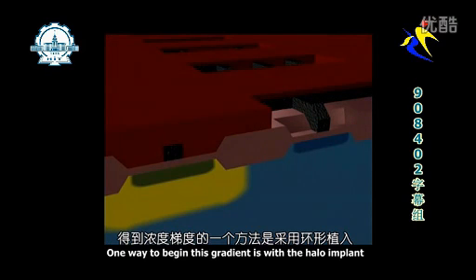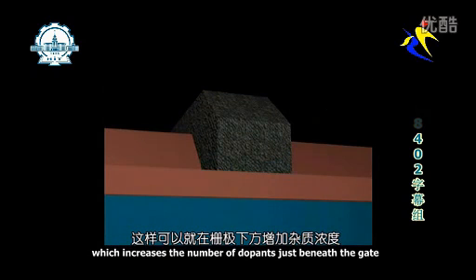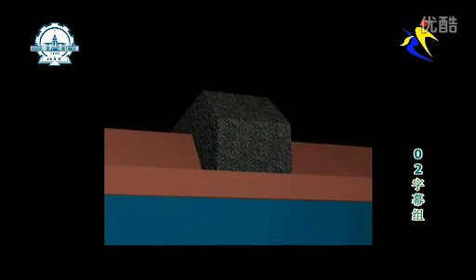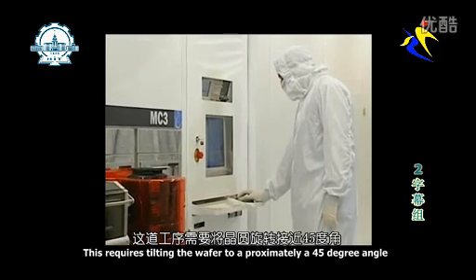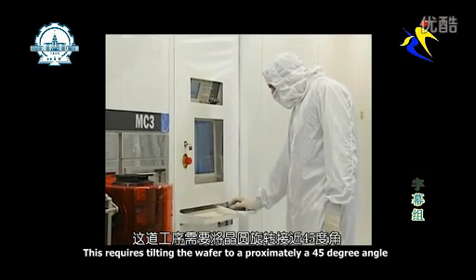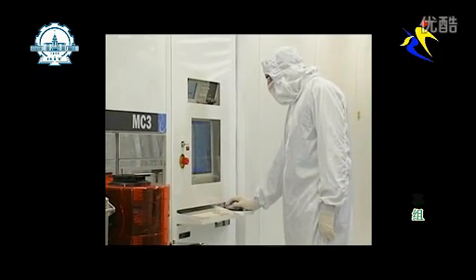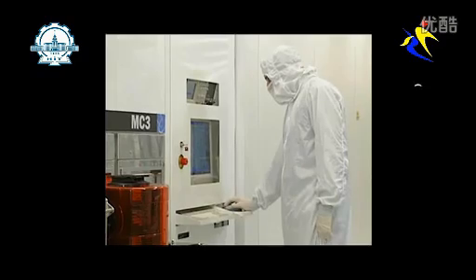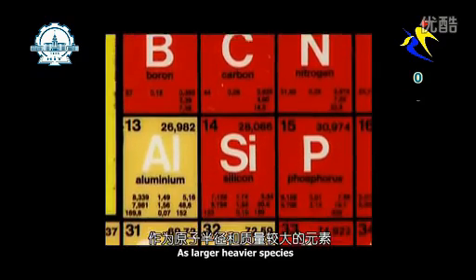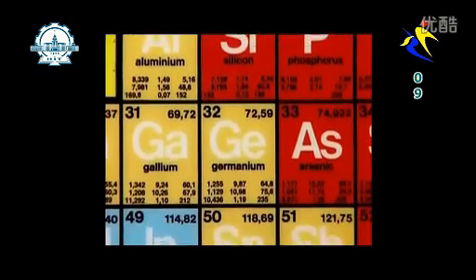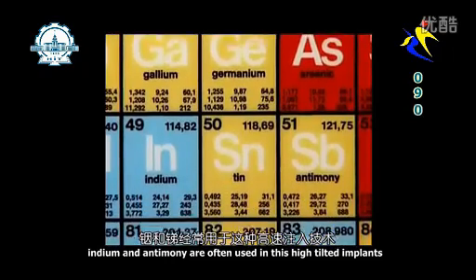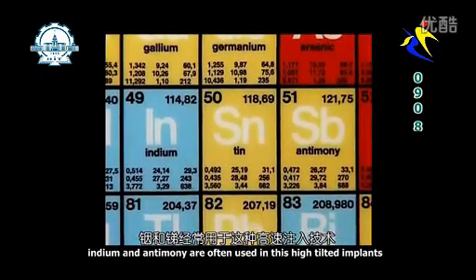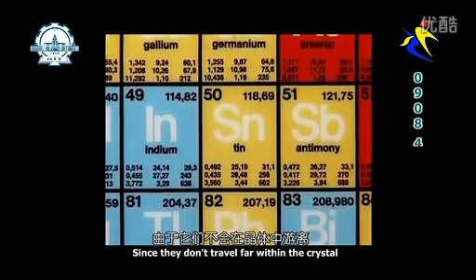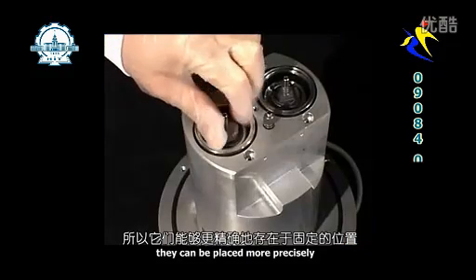One way to begin this gradient is with a halo implant, which increases the number of dopants just beneath the gate. This requires tilting the wafer to approximately a 45-degree angle. As larger, heavier species, indium and antimony are often used in these high-tilt implants. Since they don't travel as far within the crystal, they can be placed more precisely.